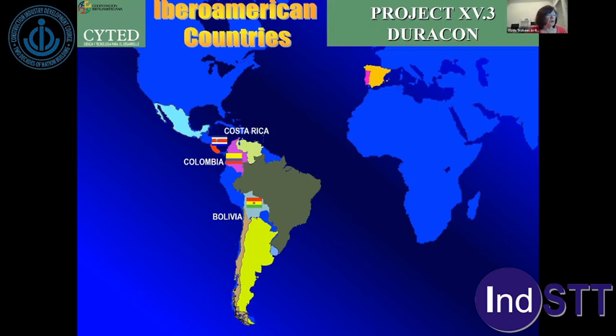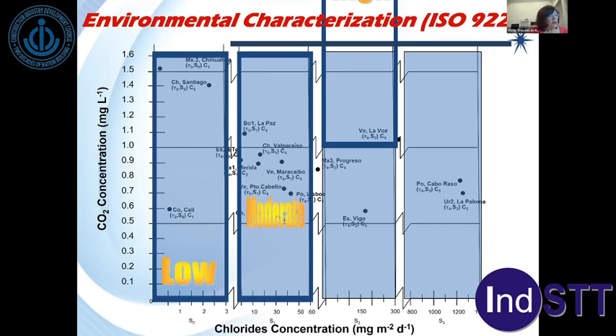However, considering that, unlike carbon dioxide and chloride ions, the sulfur dioxide contained in the atmosphere does not significantly affect reinforcement corrosion, CO2 instead of SO2 content is plotted on the y-axis in this figure, where you can see the results from all the test sites analyzed in this paper for the first year of evaluation. Notice the wide range of environments, from moderate to very high corrosivity, not only for marine environment,